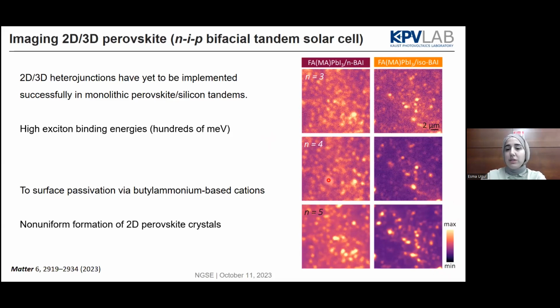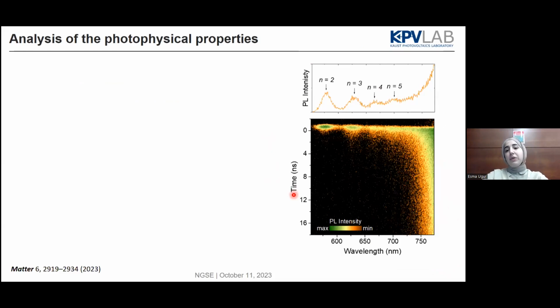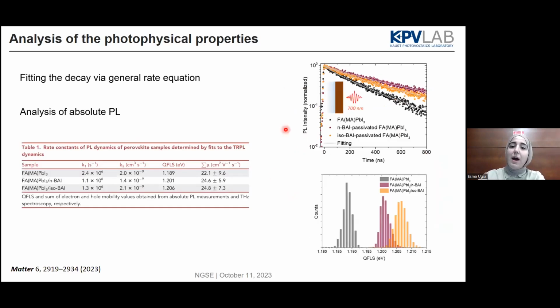So we say that we have non-uniform formation of these 2D crystals. I didn't show it here, but in the GIWAXS we can also see that we have these crystals. Then I checked the time-resolved PL. Again, you can see these excitonic peaks and how they are decaying, while the main perovskite peak is forming.